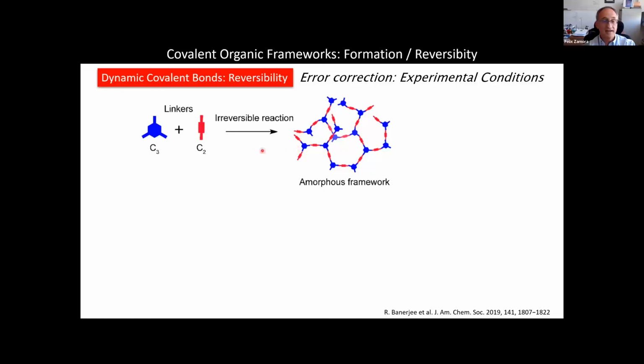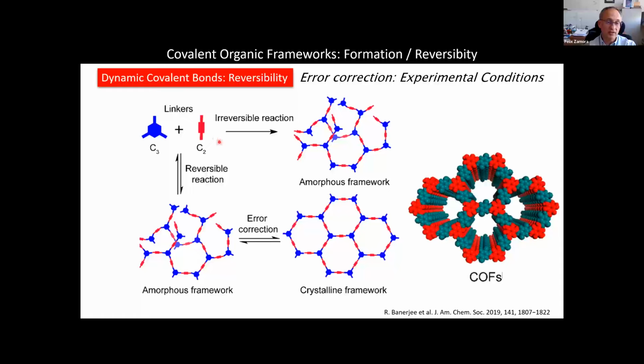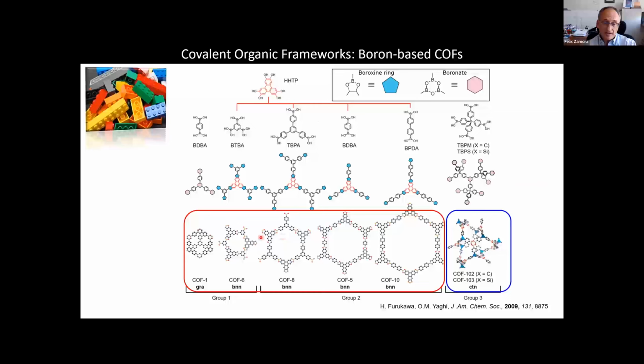Instead of that, in the case of covalent organic frameworks, we connect the molecules using dynamic covalent bonds. The meaning of that is that when you arrive at this amorphous situation, because of the reversibility of these bonds, you can correct the errors. For instance, here you can observe we have a molecule that is disconnected at that point, so you can apply experimental conditions in order to correct these errors. And then you end up with this nice ordered structure that is the most stable in terms of thermodynamics. Okay, so you can use many molecules. Here I summarize some of the works in which you can combine different boronic acids with different polyalcohols, and then you can end up with 2D or 3D structures with different pore size cavities, different architectures, and eventually different functionalities in the cavities.